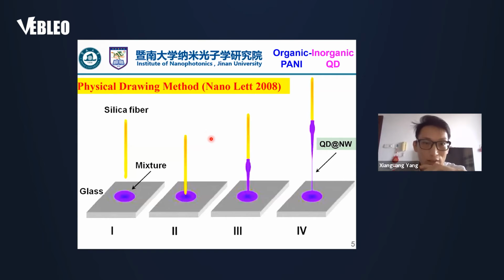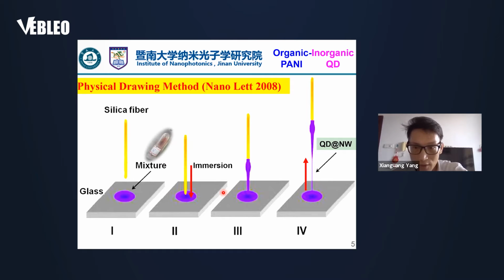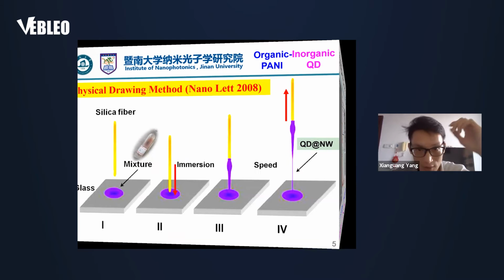In our group, we developed a physical drawing method by dissolving quantum dots into polymer. First, we obtain the mixture of quantum dots and polymer and drop it on glass, where a silica fiber will be approached to this mixture and then drawn at a speed of about 1.5 to 5 meters per second. Then a polymer nanowire containing quantum dots was obtained. This is our strategy.